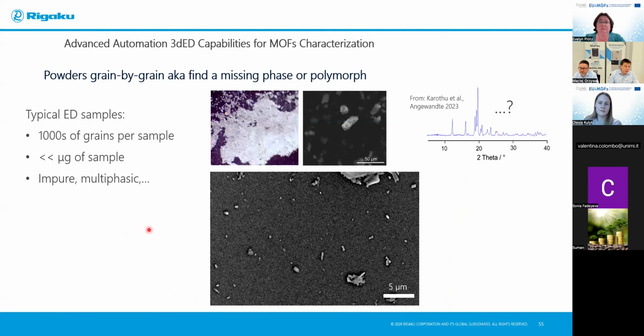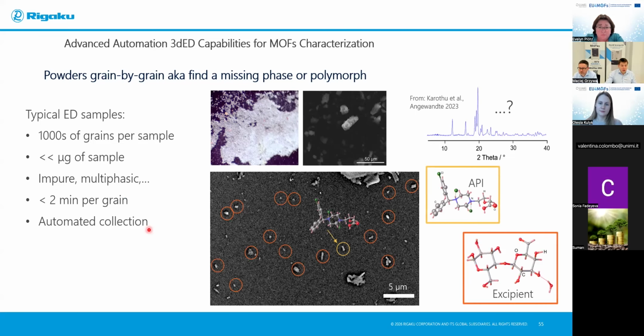Okay, so as Maciej mentioned, we do have a method that allows you to do the analysis without knowing all the phases, just using intensities. But if you want to do it with Rietveld, you need to know all the phases. And what happens if your powder pattern has something that is not in the database and it's not something that is in the chemist's notes, and you are completely lost? So you go back to electron diffraction, as we extended our cluster analysis and batch processing to electron diffraction. We do also support the plates in transmission mode on the single crystal instrument, similar to SmartLab, but with electron diffraction, you can do what we call grain by grain, or sometimes, as I call it, missing phase or polymorph search, because it can go automatically phase by phase with completely unattended measurements, find the grains, center and measure them, and combine everything.